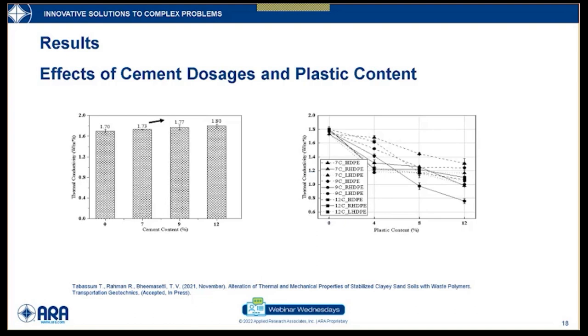Whereas when the soil was mixed with different plastic contents, starting from 4 to 12%, and depending on the different forms of recycled plastics, like small regrind or long pellets, the thermal conductivity decreases as the plastic content increases. This is also due to the density. As the plastic content increases, the density of the soil mixture decreases because the plastics have low density, like 0.9 gram per cc, than the cement and the soil itself. So as the plastic content is increasing, more volume is occupied by the plastics in the soil samples. So there is less soil particle to particle contact, and thus the thermal conductivity decreases because there is no way to conduct the heat. The minimum thermal conductivity was observed when it's mixed with 9% cement and 12% regrind HDPE, and it was almost 0.75.